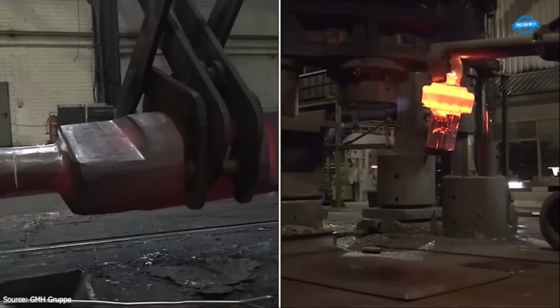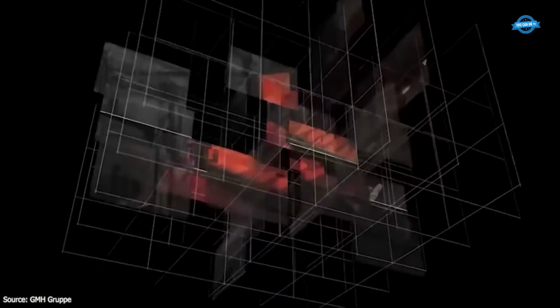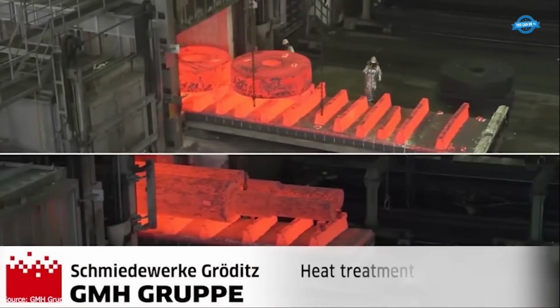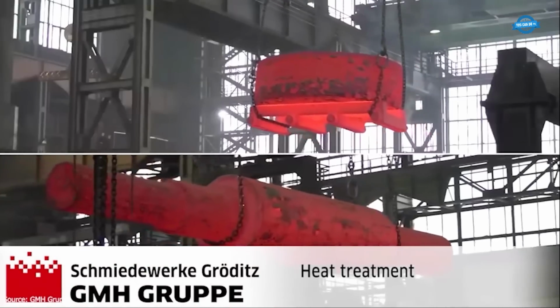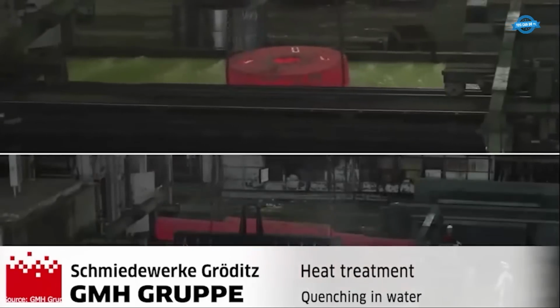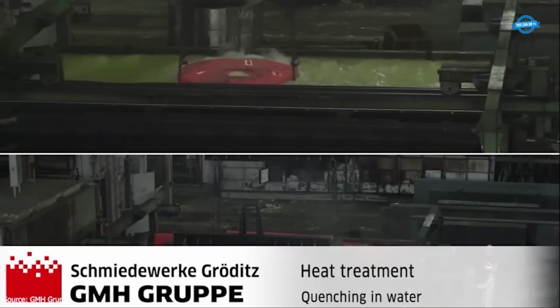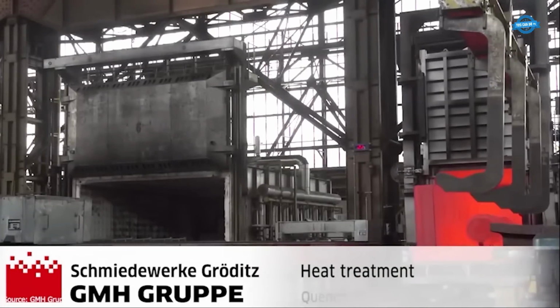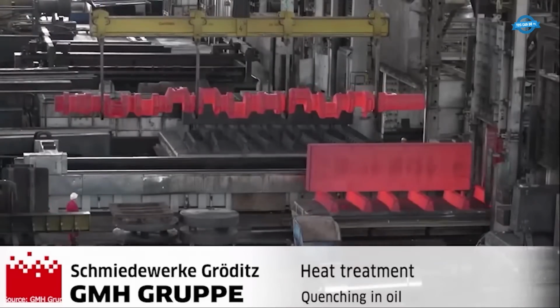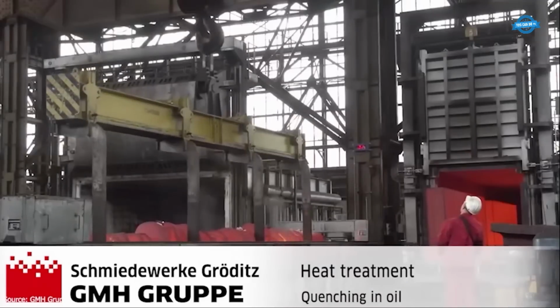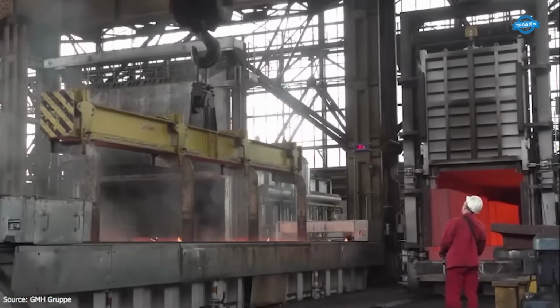Post-forging, parts undergo heat treatment in calibrated bogie hearth furnaces and are quenched in temperature-controlled oil or water tanks with high circulation capacity. For components up to 8.5 meters in height requiring high concentricity, vertical heat treatment is available. After heat treatment, forgings are machined.